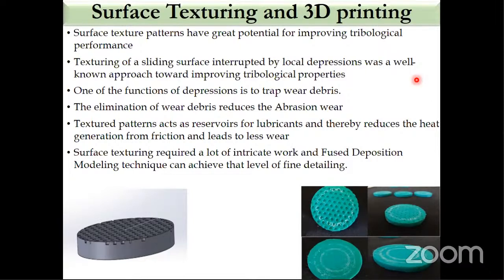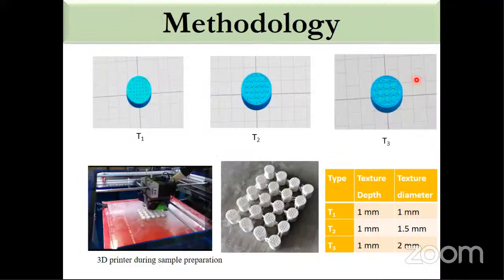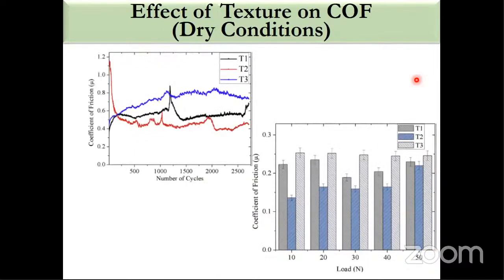So surface texture requires a lot of intricate work, and it is a little bit difficult by conventional processes, but the fused deposition modeling technique can achieve it very finely, and we have done it in our lab. We selected 3 different textures on the basis of previous literature, and then varied the texture depth and the texture diameter for the different samples, and then we tested it for the coefficient of friction at dry conditions, and we could see that texture T2 is performing well, and you can see here also that at all loads, we checked it for different loads, and texture T2 proved to be better in comparison to the other 2.